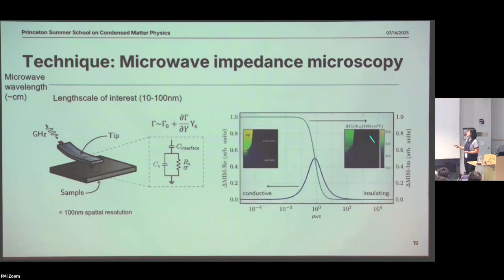But also because it's only a perturbation, the real and imaginary parts now do not have a one-to-one correspondence with sigma prime and sigma double prime, or to say, it doesn't have one-to-one correspondence with the dissipation part and the inductive part. Instead, here we can do some finite element simulations to get a different dependence. So the y-axis is the sample resistance, and omega being the frequency, and also the permittivity.